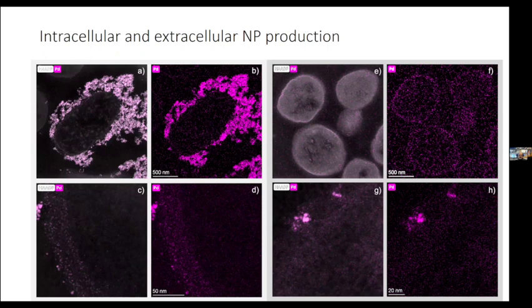This is EDX electron microscopy to prove to you that the particles we're getting are indeed palladium particles. This is a specific palladium signal. On the four pictures on the left you see here is a situation corresponding to the wild type, where most of the particles are formed on the surface of the cell in the extracellular matrix. On the right hand side, we see that the strain has the particles mostly inside the cells, and that they are on average much smaller. Everything in pink here is palladium. The particles in that case are inside and smaller, and this is the one strain that I showed you earlier has also the highest catalytic activity in our test reaction.